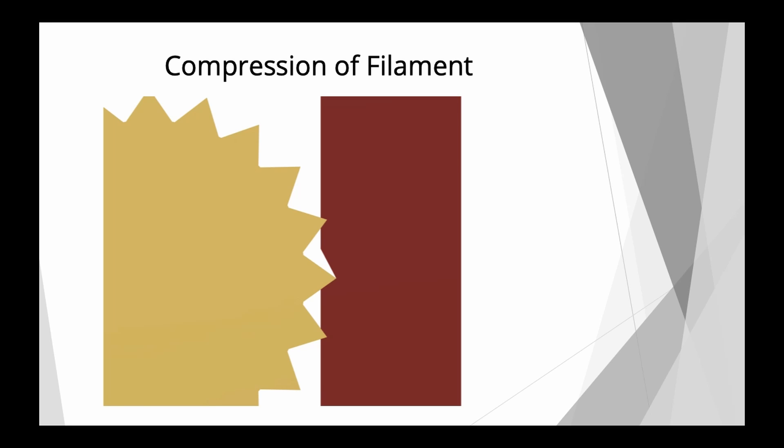And that is because filaments don't like to be pushed through hotends. It tries to get around it somehow, because you need pressure to push the filament through the nozzle. And the filament doesn't want to go through that nozzle, so it tries to find a different way to compensate for the pressure. So what it does, it basically bulges up. The drive gears, the teeth of the drive gear, push onto the filament and then compress it, and really try to compress the filament to get it through that nozzle. And this compression has to be compensated, and that's why you get a higher e-step value.